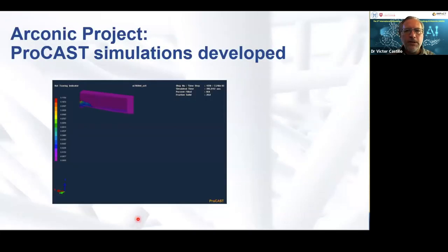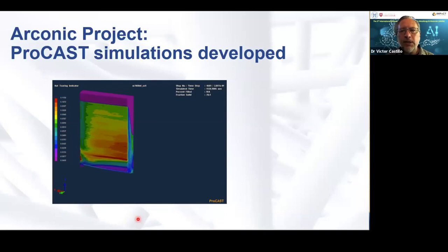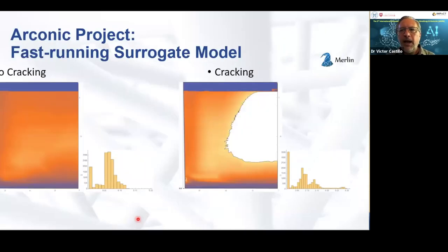So what we can do is simulate where the residual stress is, and predict it. These simulations take about 24 hours to run, 24 to 36 hours. What we're doing is learning from the simulations, and the fast-running surrogate model, like the one for the glass, can predict the output in seconds.